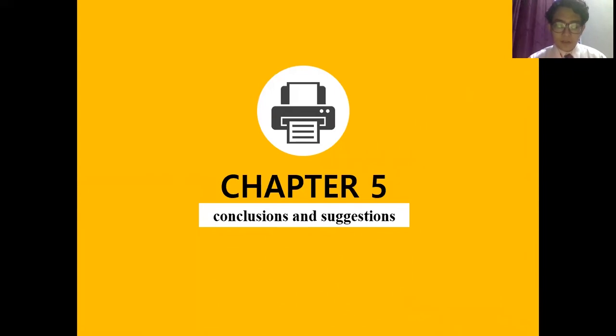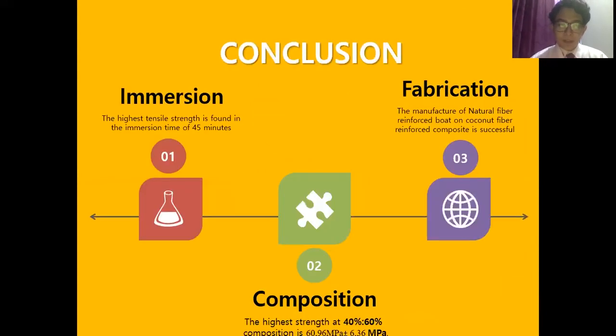Okay. The last chapter is chapter number 5, the conclusion and suggestion. The conclusion of this research: first, immersion. The highest tensile strength is found at an immersion time of 45 minutes. Second, composition. The highest strength is at 40% fiber and 60% matrix composition, at 60.96 MPa with a deviation of 6.36 MPa. And the last is fabrication. The manufacture of natural fiber reinforced composite from coconut fiber is successful.